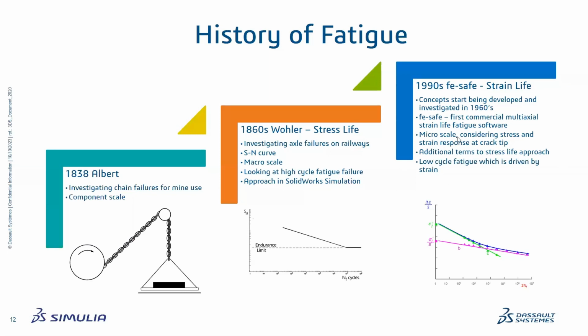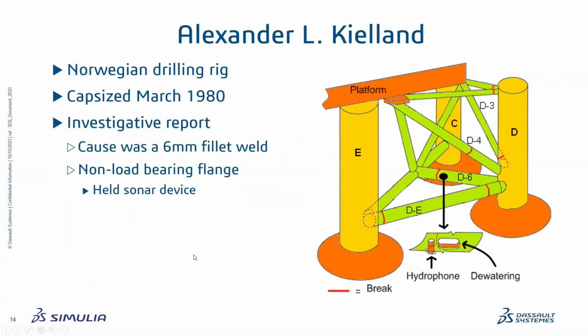But what's nice about this is that it actually enhances the stress-based approach, looking at a crack tip and at micro-scale ideas to get the plastic straining at the crack tip and then incorporating that. And where this really comes in is that instead of looking at the very high cycle fatigue of railway axles, you're now pushing back to lower cycle fatigue failures, where the plastic strain at the tip tends to start dominating the fatigue damage that is accumulating. But the bit that I was really trying to get to was welds.